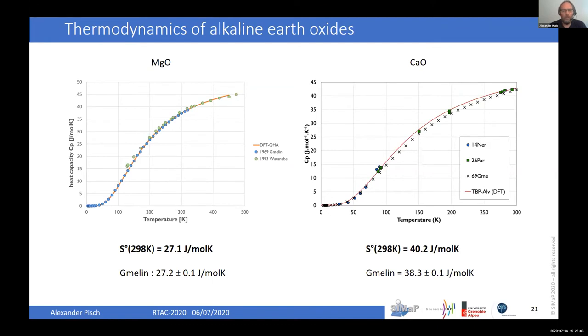On the left side, you see magnesium oxide, and you see a very, very good agreement between the work done by Gmelin in 69 here in Grenoble and work by Watanabe in 93. And the calculated entropy is basically exactly the entropy that Gmelin derived from his measurements. So that was very satisfying. And so we said, okay, let's try calcium oxide and strontium oxide.